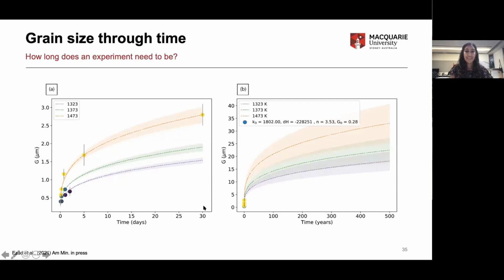Experiments longer than 30 days are near on impossible to run. So we need a better approach to what we do with the grain growth kinetics. The grain growth kinetics are fantastic for telling us what the mechanism of grain growth is, what the diffusive species is, and the way in which those grains are coarsening. But really, we need to be able to constrain the grain growth exponent, which is the rate at which those grains are going to grow over geological time. So I think we need a better computational and experimental approach to solving that problem for grain growth kinetics.